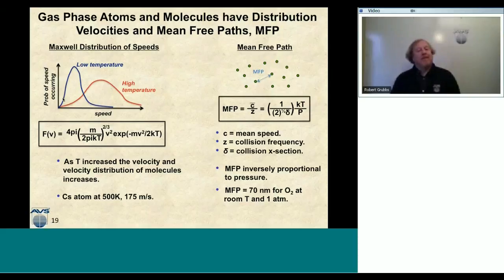But then as I heat that gas up, we can see what happens to the distribution of the speeds. Not only does the average speed move to higher speeds with higher temperature, but the distribution of the speeds actually increases as well. And so that can be important. Sometimes in plasmas, where you have a very high temperature plasma, you get this high temperature wing of very highly energetic particles in your plasma because it's so hot. This has a tendency to damage the film because you have this little wing of very high temperature ions moving at such high velocities, smashing into your surface, and that's something you may not want.